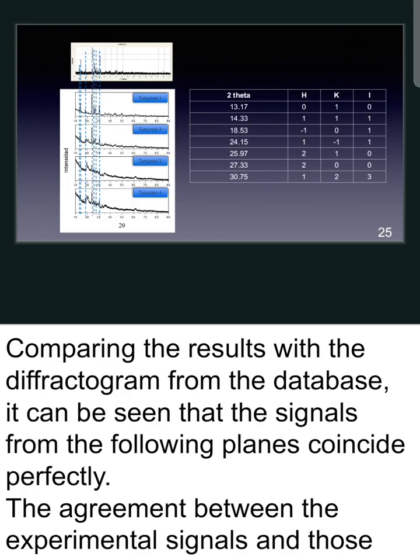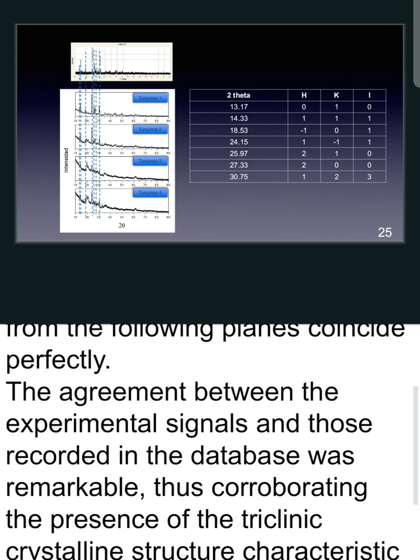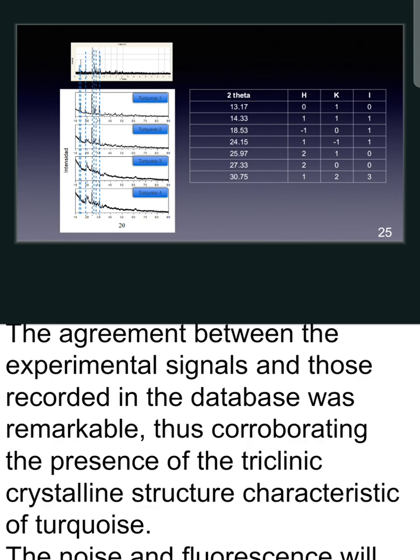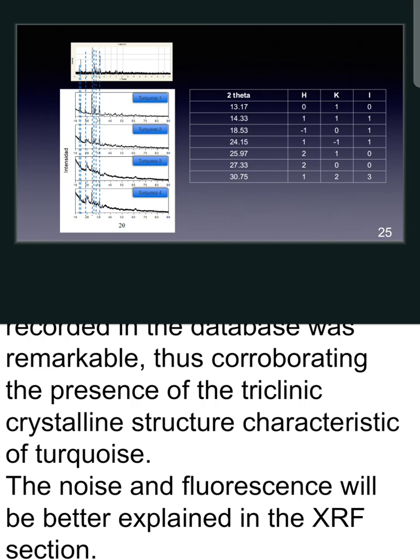Comparing the results with the diffractogram from the database, it can be seen that the signals from the following planes coincide perfectly. The agreement between the experimental signals and those recorded in the database was remarkable, thus corroborating the presence of the triclinic crystalline structure characteristic of turquoise. The noise and the fluorescence of each diffractogram will be explained in the X-ray fluorescence section.